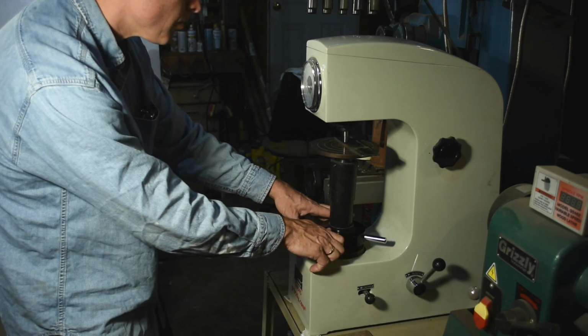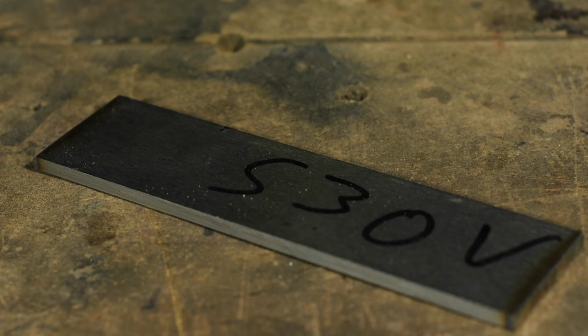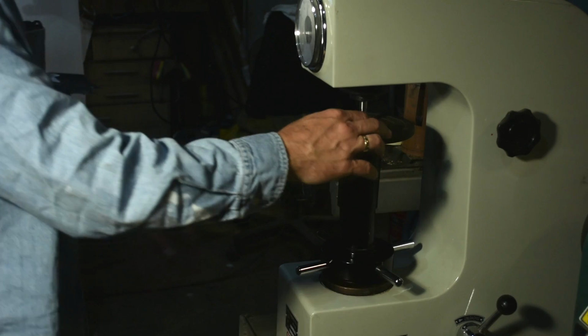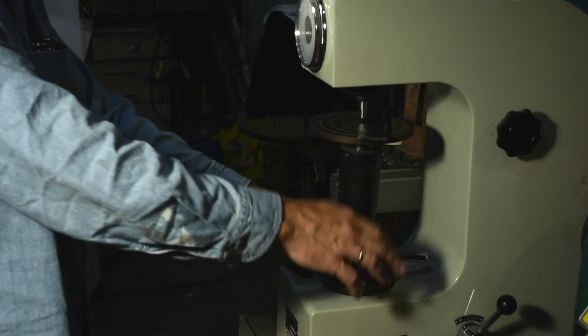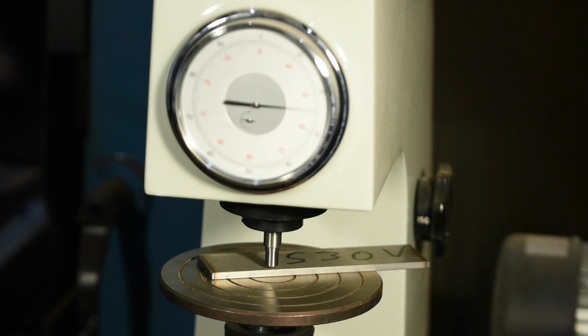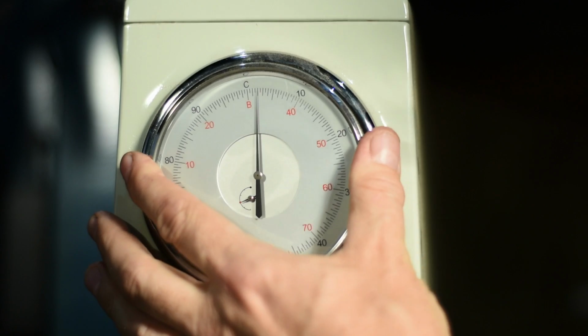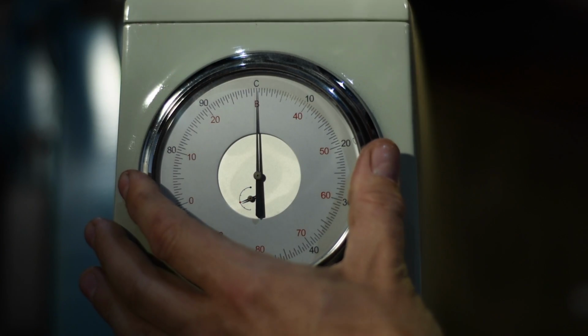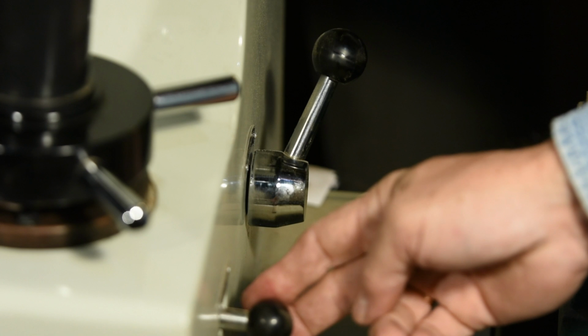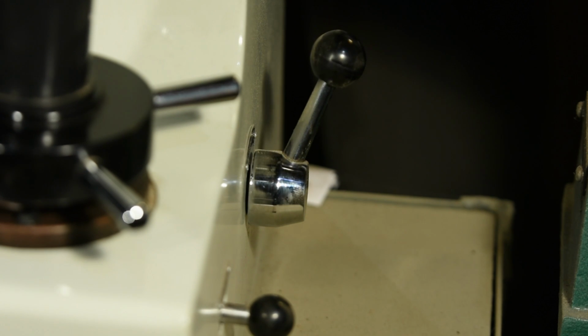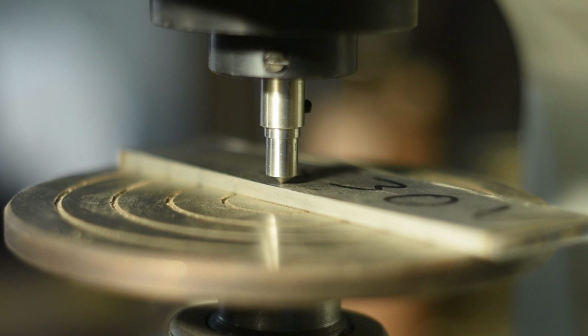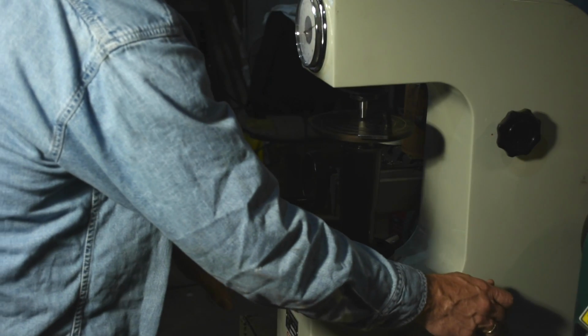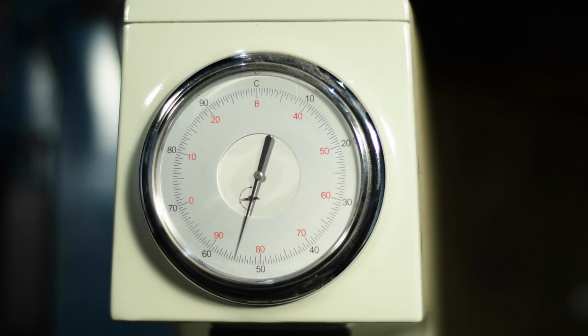So, watch as we test a sample of unhardened S30V. This is basically just the way it comes in from the mill. We're going to place the sample on the table. There's a preload phase. Once we've got it preloaded, we set the dial so that it starts at exactly the same place every time. Now we give the probe its main load and it's going to squash that diamond down into the sample and sort of smush out this tiny little hole. The final Rockwell number shows up on the black number scale on the outside of the scale. So it comes out to about 23 or 24 on the Rockwell scale.